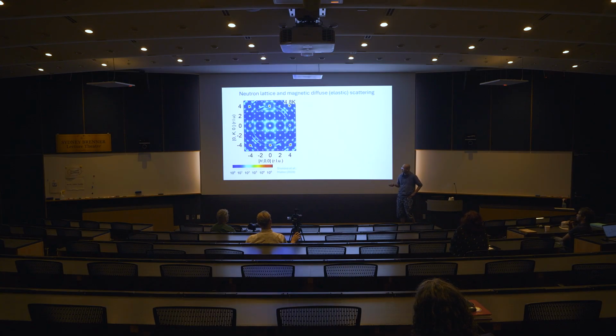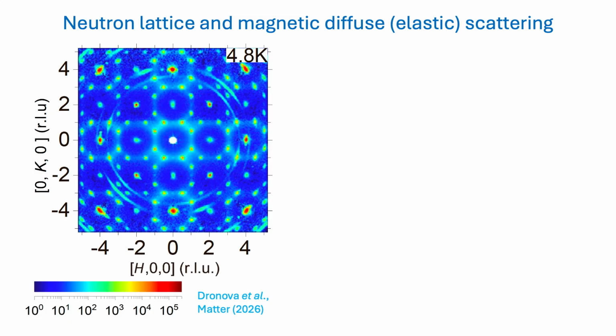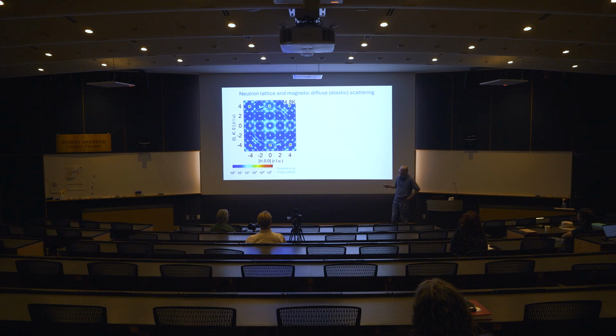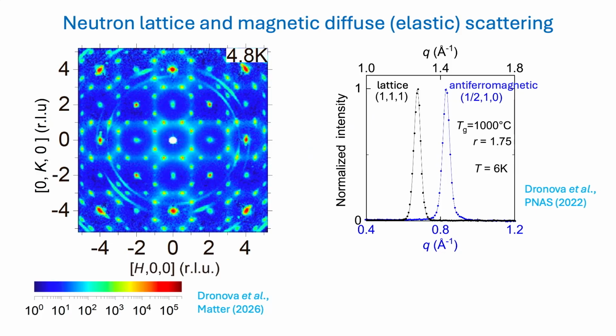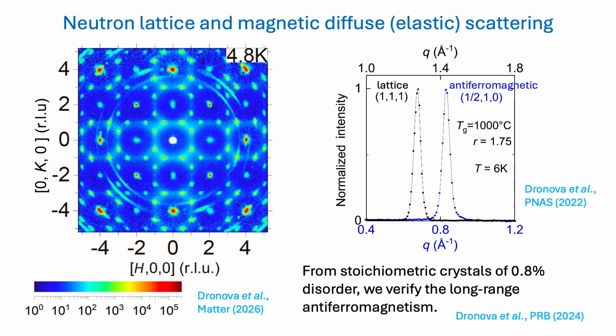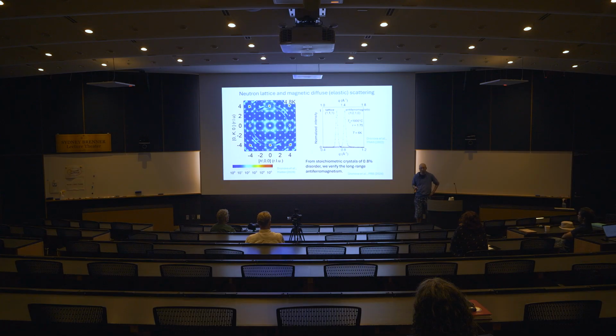We brought our crystal to the neutron beamline. You can see here we have single-crystal behavior, with the magnetism and the lattice indistinguishable from each other. This intensity is plotted on a log scale, so you actually have very low diffuse scattering here. And this is only our second best sample. By studying the line width of this material, we can verify this long-range order is as long-range as our crystal itself. So basically, we actually cleaned up the crystal.